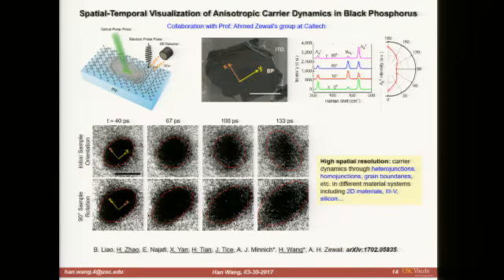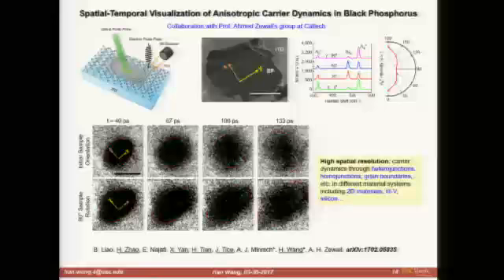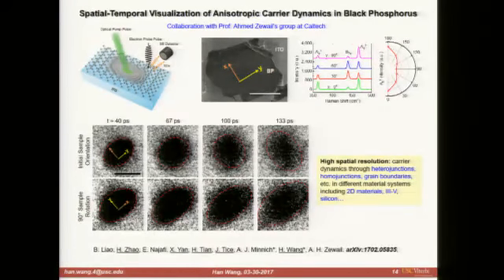As I mentioned, one of the key benefits of this new technique is that you get much better, much higher spatial resolution in the images. So this is kind of an ideal technique for looking at carrier dynamics through, for example, lateral heterostructures or homojunctions, or through grain boundaries, how carriers go through the grain boundaries, which was previously impossible using optical pump probe measurement - you just don't have the resolution to see that. Here you are at the nanometer scale resolution.